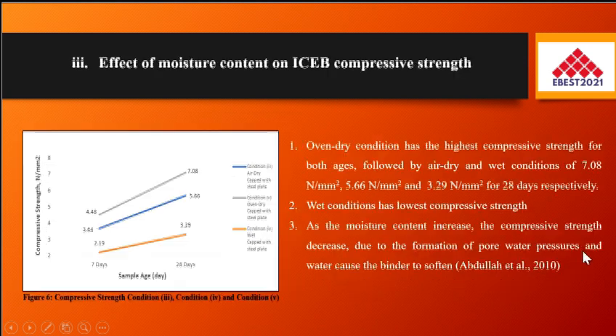Last but not least, the effect of moisture content on ICEB compressive strength. Figure 6 shows oven dry has the highest compressive strength for both ages, followed by air dry and wet condition. Wet condition has the lowest compressive strength, which is comparable to the research carried out by Abdullah et al. 2010, which stated that as moisture content increased, the compressive strength decreased. This is due to the formation of pore water pressure, and water caused the binder to soften.